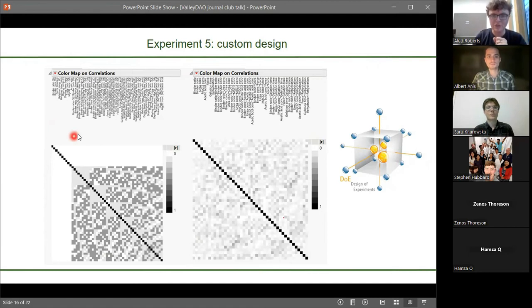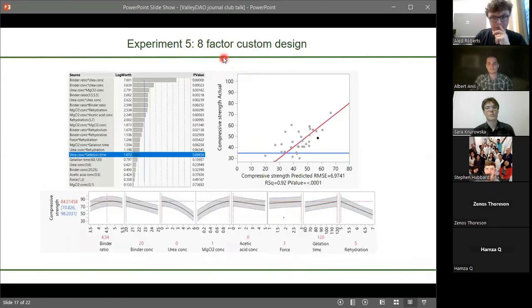And then this custom design was 56 experimental runs, and essentially it gives you much higher resolution of the experimental space. It picks out all the experimental combinations to get you the maximum amount of information from this complex experimental space. And by now there were fewer factors as well. So it's more experimental runs, fewer factors, but much better resolution. So it tells you a lot more about what's going on in your system. It was an 8-factor custom design, and essentially it gave us a lot of useful information.